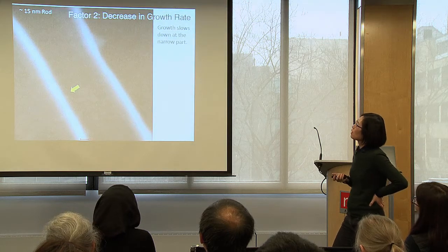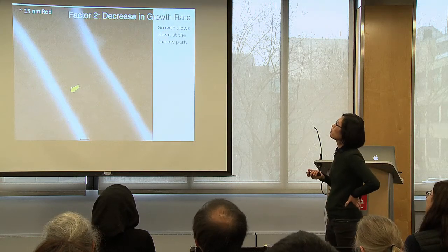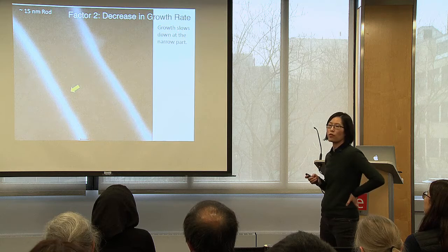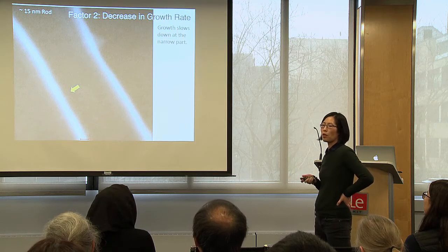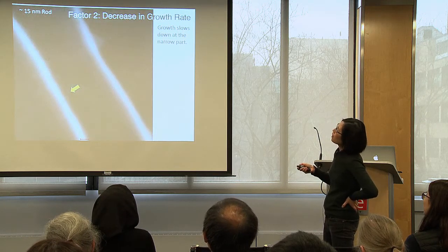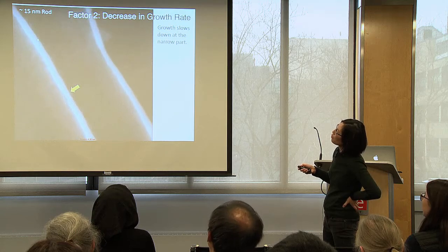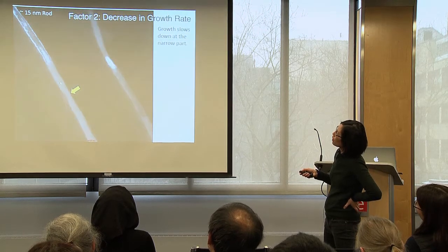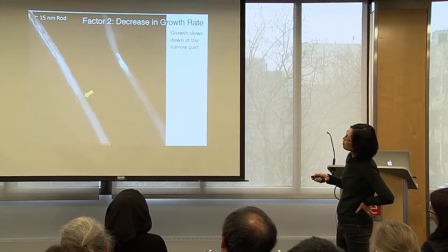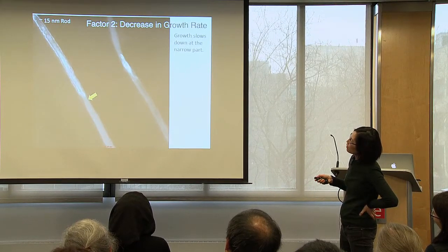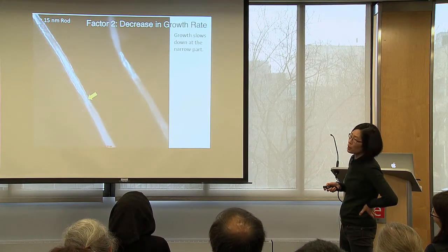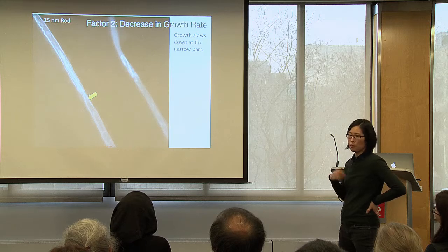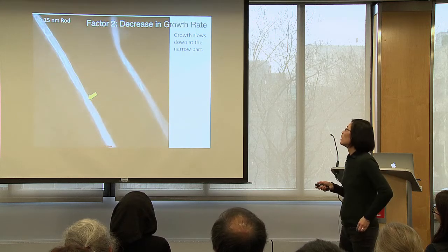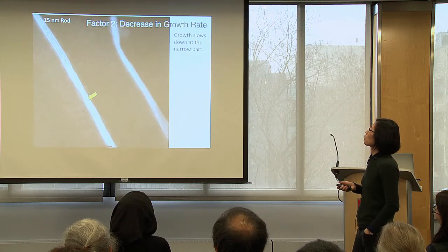The second one is from the observation, and that is that the growth rate itself also slows down for small rods. So here is a movie. You're going to see the grain growing, and then it develops a necking here where it's a little bit narrower. And then the grain growth gets suppressed quite a bit. Once it passes, it picks up the speed again. Okay? So in the narrow region, the growth rate slowed down.